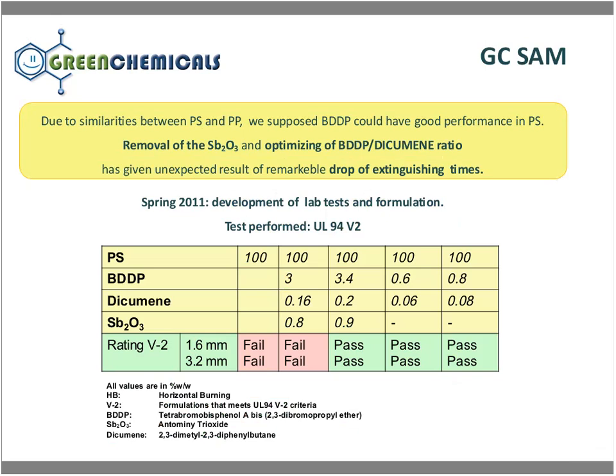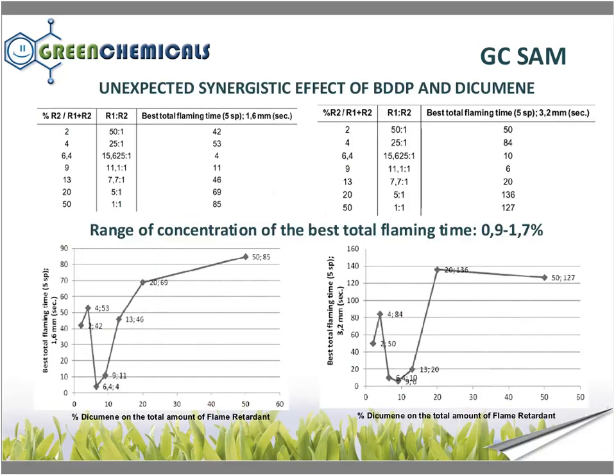And what we found was that the removal of the antimony trioxide gave us the opportunity to pass the test with a very low dosage of the brominated molecule. Another point that we found was that the optimization of the ratio between BDDP and dicumene was very important. Actually, we understood that the synergistic effect between the BDDP and its synergist, the dicumene, was obtained only within a specific range of values.